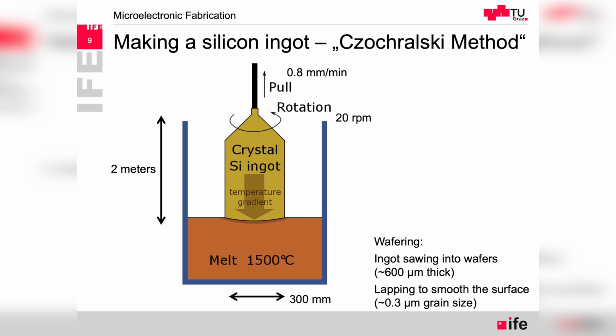with a speed of approximately 20 rotations per minute and 0.8 millimeter per minute pulling, so really slow. You can see that it will take a really long time to achieve an approximately 2 meter rod, of which we cut wafers of approximately 1 millimeter thick, so we have plenty of wafers from that. But the process is really expensive and takes a long time, because not only is everything made slowly, but then very slowly it has to cool down to room temperature before the next treatment.